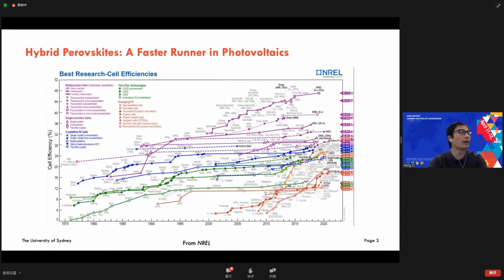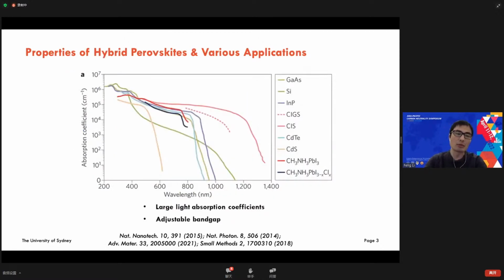This material is already treated as a star material. From this picture, we can see that solar cells based on this material have developed very fast. Currently, the efficiency is approaching 30%. It's quite a promising material. So why can this material be developed so fast in the photovoltaic field? That's because this material has excellent properties, like a very large light absorption coefficient,